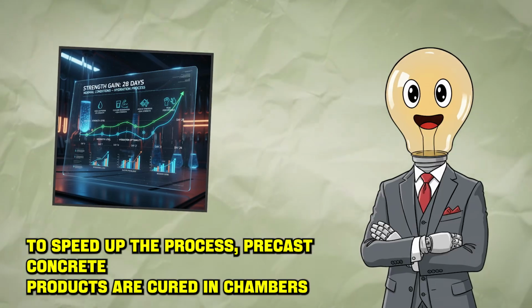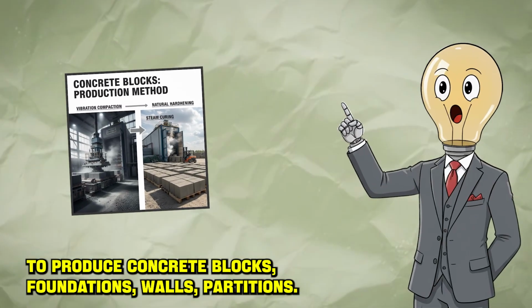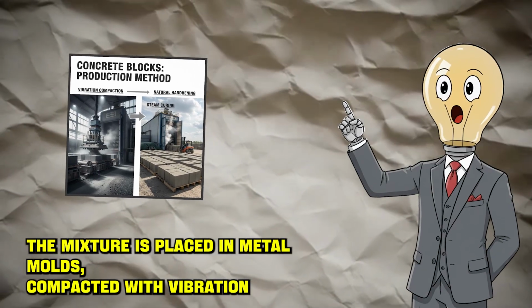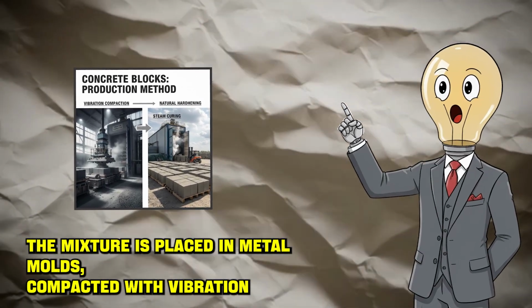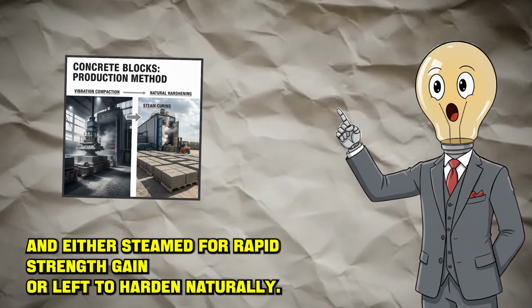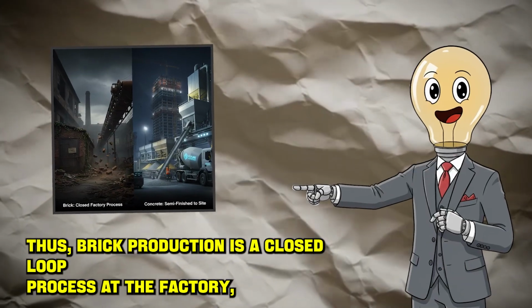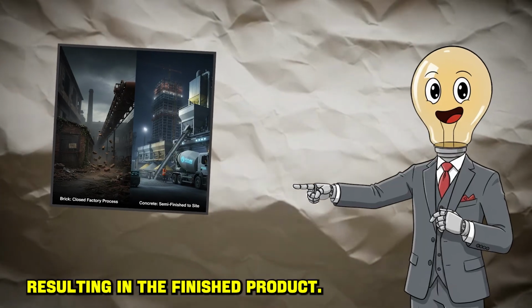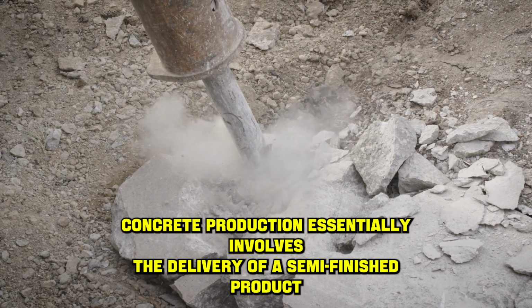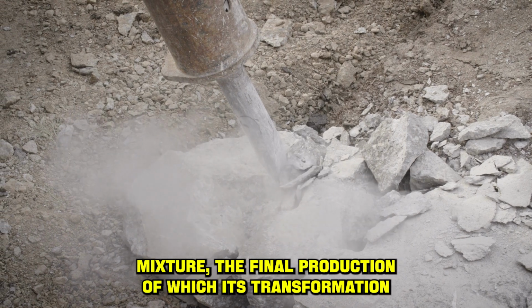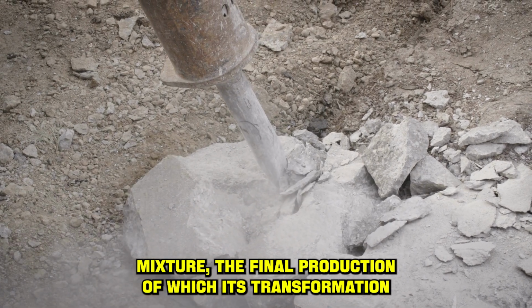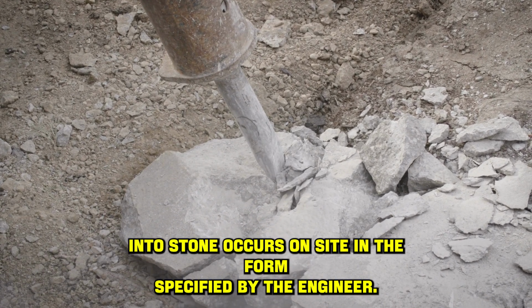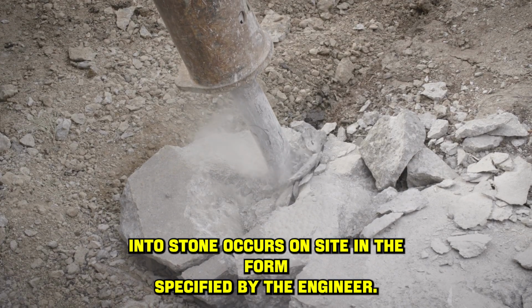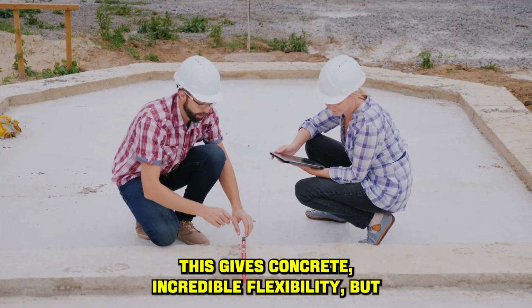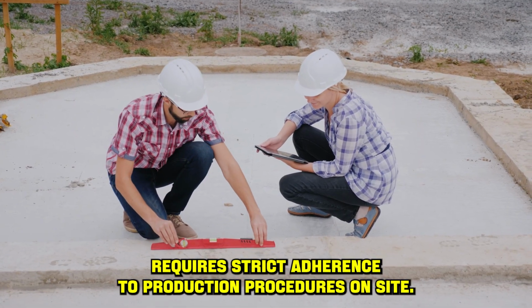To speed up the process, precast concrete products are cured in chambers. To produce concrete blocks, foundations, walls, partitions, the mixture is placed in metal molds compacted with vibration and either steamed for rapid strength gain or left to harden naturally. Thus, brick production is a closed-loop process at the factory, resulting in the finished product. Concrete production essentially involves the delivery of a semi-finished product, mixture, the final production of which, its transformation into stone, occurs on-site in the form specified by the engineer. This gives concrete incredible flexibility but requires strict adherence to production procedures on-site.